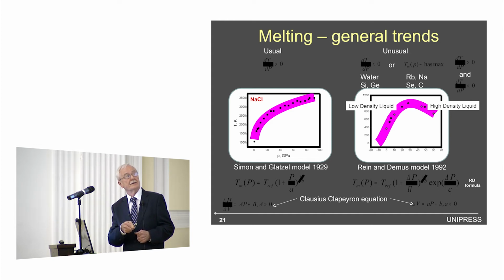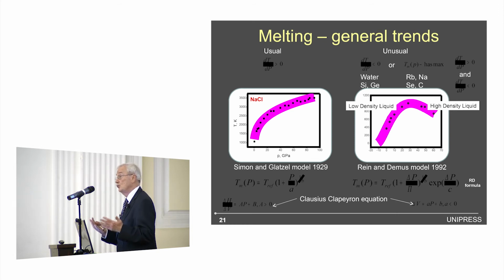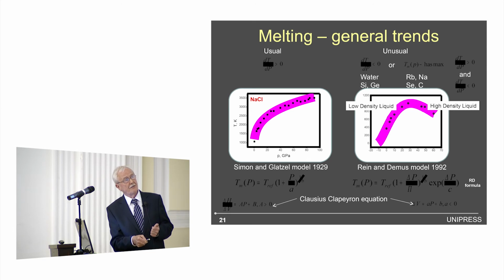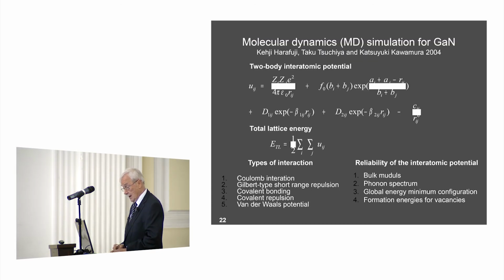And this maximum of melting is related to a structural change in the liquid. We have two types of liquid: a low density liquid here and a high density liquid here. And the change of the behavior under pressure is related to the change in the liquid. That's the formula which can be used to describe this kind of dependence, and it works for these materials very nicely. Van Vechten's theory did not include the possibility that there might be two liquids and a change in the local structure of the liquid under pressure.